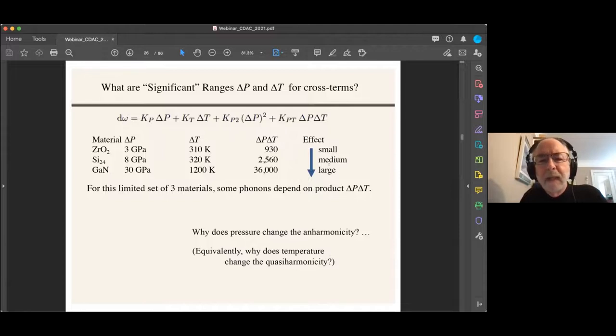And we could get some big effects if we're at very high temperature changes and high pressure changes in this cross term, which we had in a multiple parameter fit. And then we got out the linear and the pressure-temperature quadratic here in this cross term. Now, the product of these suggests that we might need about 5 gigapascals and about 500 Kelvin to see effects well in a typical material by neutrons. And I think we could see changes in the phonon dispersions under those conditions. But we're not quite there yet.